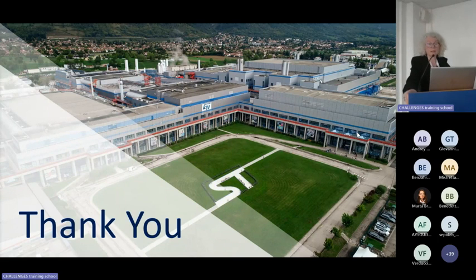Yes, for sure. We have to model this, because obviously the size is important. We also have some equipment, especially for dielectric layers, like nitride, those kinds of things, that will create some high stress. So we had to adapt the film and the thickness to have something flat.